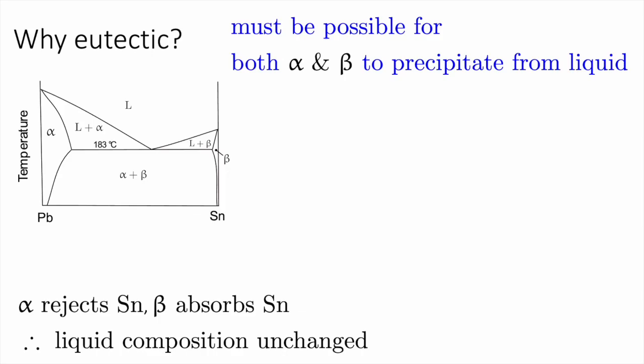Now, it's interesting to ask why the eutectic reaction happens at all. We've already got one reason: the solid mixture, which has the eutectic microstructure of alternating alpha and beta, has the same average composition as the liquid. So solute does not need to diffuse and enrich the liquid at all. That makes the reaction rapid.